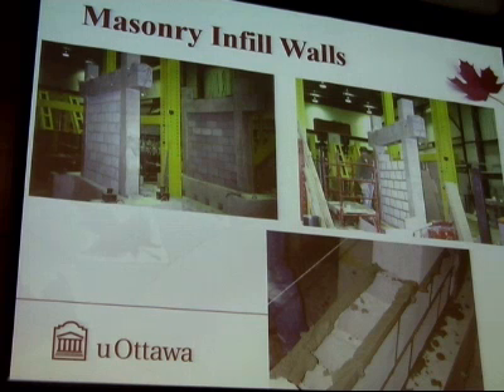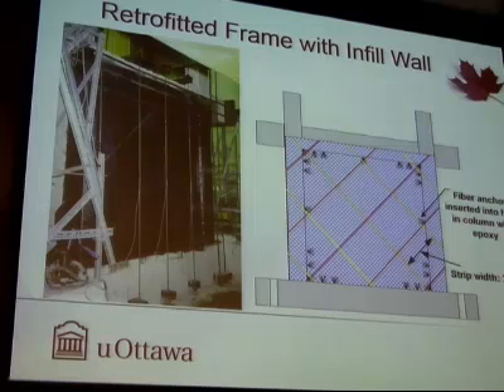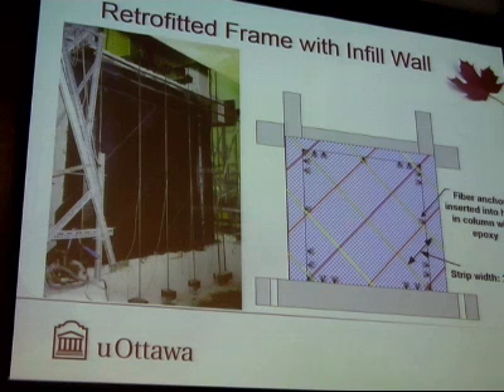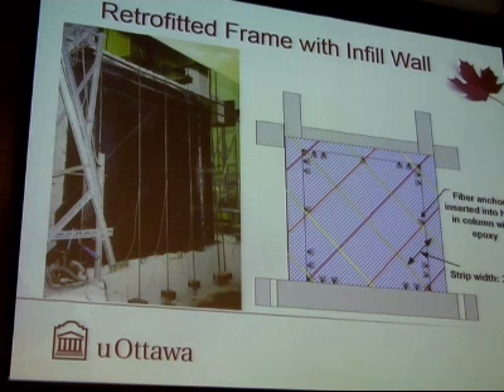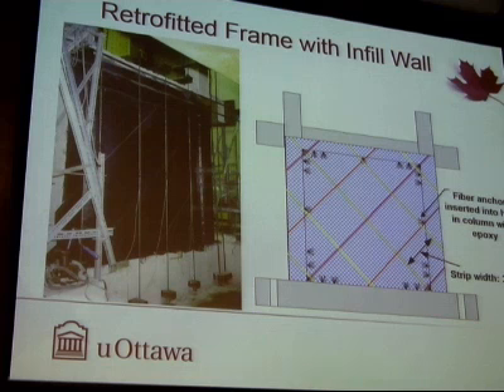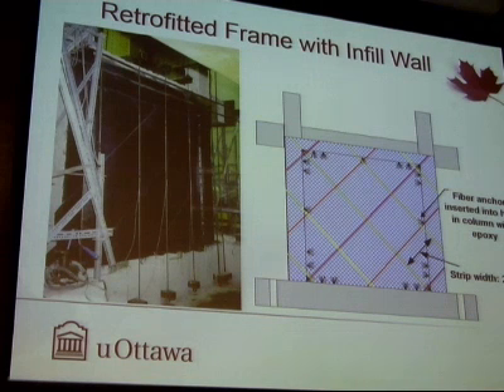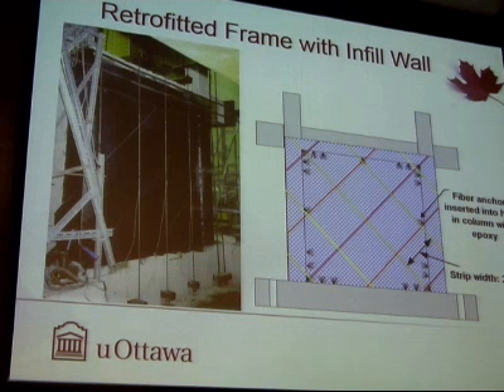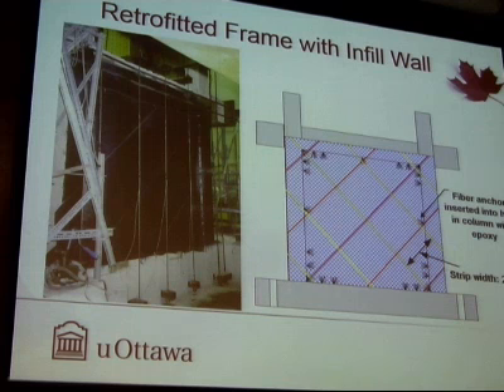Now I would like to say a few words on masonry research, first starting with infill walls, and then we'll look at masonry alone. We have done some research on use of surface-bonded carbon FRP sheets on infill masonry. The intent here was to convert this non-ductile infill masonry wall into an equivalent shear wall, which would act along with the enclosing frame, which then requires a lot of anchoring. Obviously when you use surface-mounted FRP, a very high-strength material, on masonry, which is a relatively low-quality, low-strength material, there's an incompatibility problem, and bond becomes a very significant issue, and hence we had to come up with homemade FRP anchors, and we used them to improve continuity.